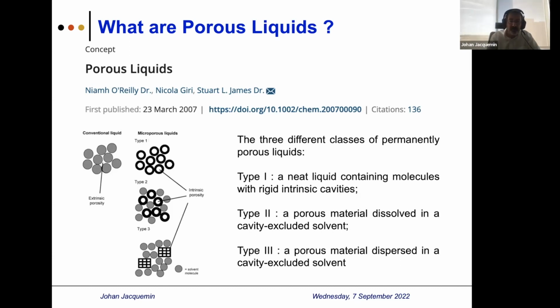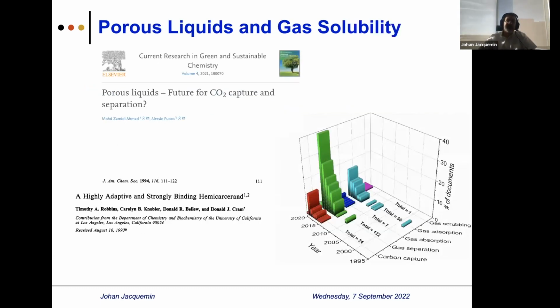However, type 2 and type 3 are more cost effective than type 1, because for type 1 you need a very good organic chemist to help you design a liquid with rigid moieties, I would say, to allow porosity. Just to give you an overview, porous liquid was originally defined in 1994 for gas sorption, with the original work from Robbins. But it's only after 2007, with the publication of Stuart James, that there is a boom.